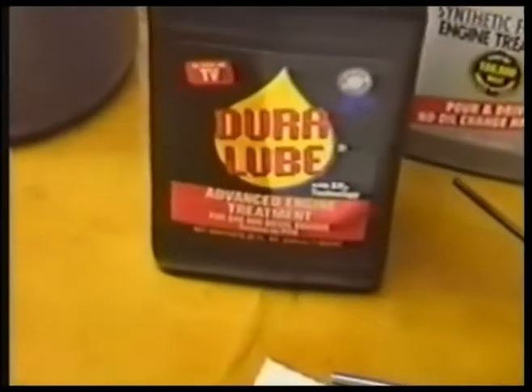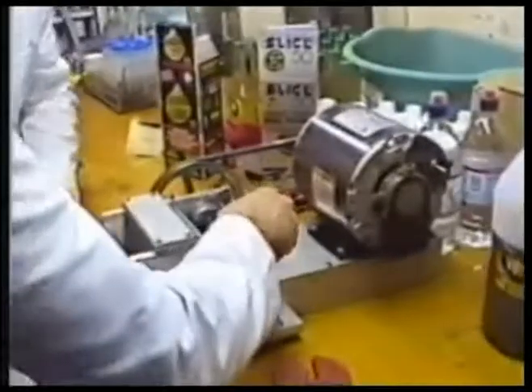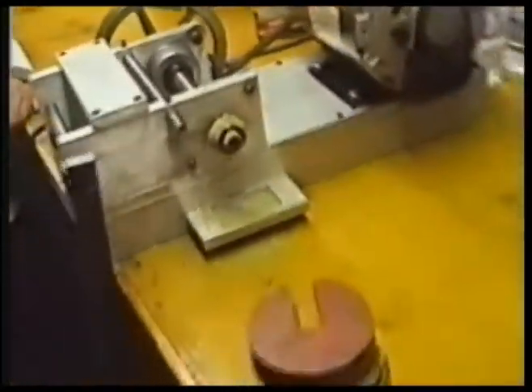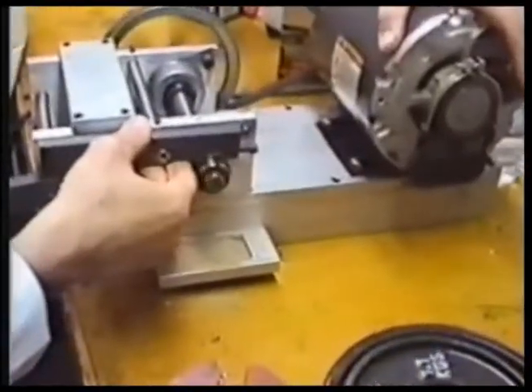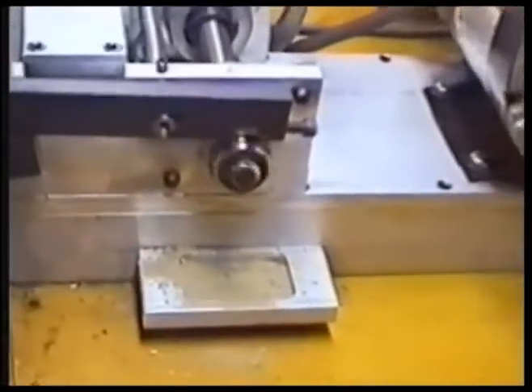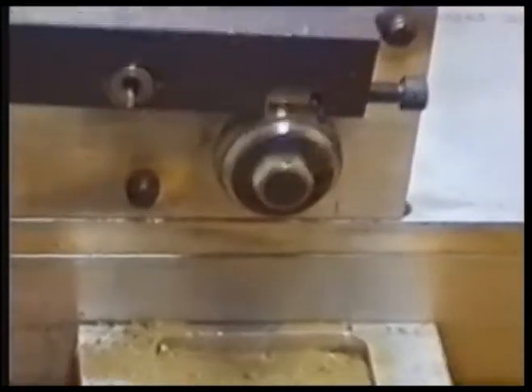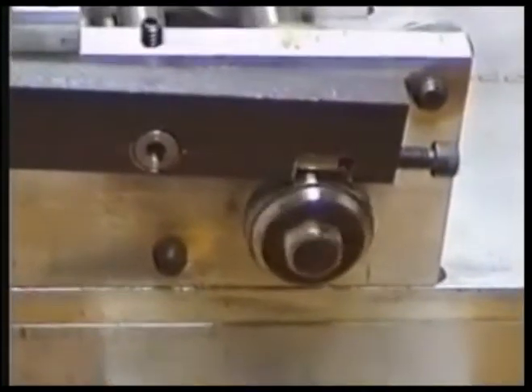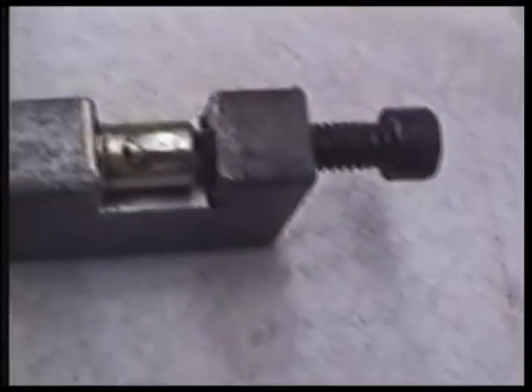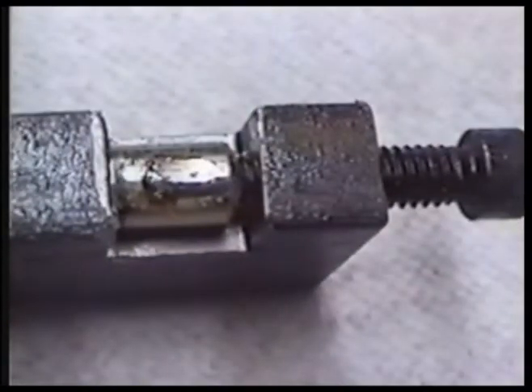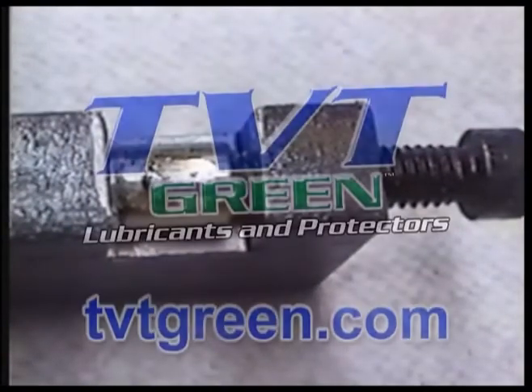As a final comparison, sand was applied to the test surface with Duralube. Catastrophic failure occurred within 2 seconds of applying the test pressure. Right there. Okay. TVT Green was the clear winner when compared against the 5 best-selling lubrication additives.